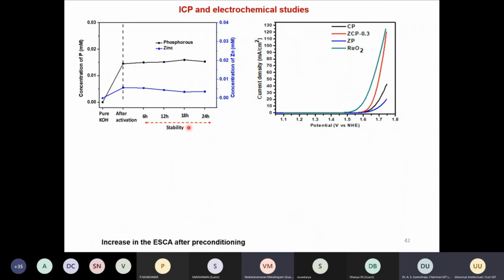And what we have done here is, again, we have measured the concentration of phosphorus on pure KOH after activation, and then we have studied this with ICP analysis. We did the electrochemical studies, took the electrolyte sample at different times, and what we found is that initially there is an increase in the concentration of zinc, but zinc leaching is not much compared to the phosphorus. That means that the phosphate etching happens at the surface.